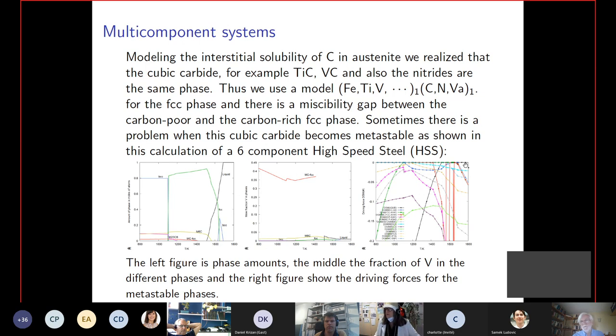So the curve here is the liquid phase. It's stable up here, but then it disappears. And you have the BCC phase, which becomes stable here, then it disappears, and then it comes back here. So one can understand a bit how the different phases relate. And of course, you don't measure the metastable phases normally. So this is extrapolated from properties you can measure.